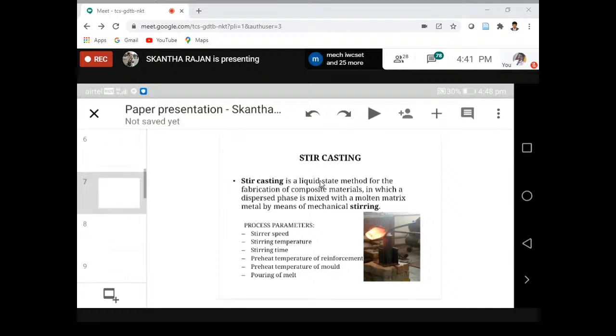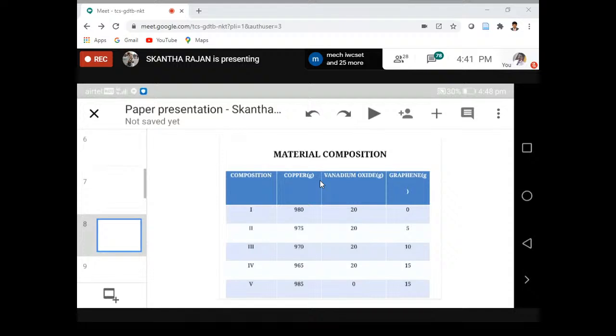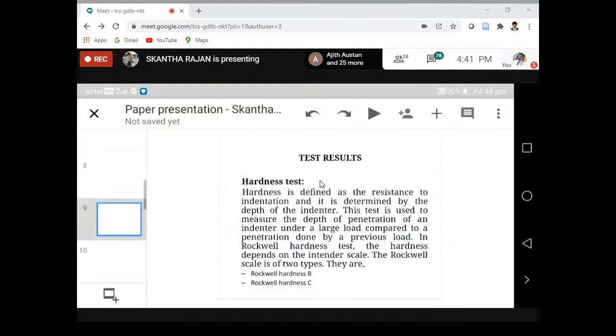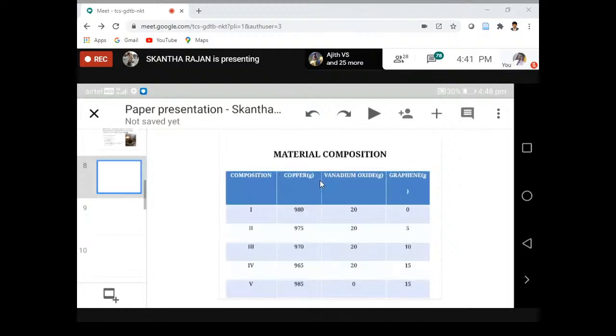Next, from the stir casting process, we have prepared five different composites for our project. These are the five different composites. In our project, we melted the copper at 1200 degrees Celsius. After that, we added the reinforcements like vanadium oxide and graphene. The vanadium oxide and graphene are preheated at 800 degrees Celsius before being added to the molten copper. If they are not preheated, it will form pores inside the material. So preheating is a very important thing in the stir casting process.